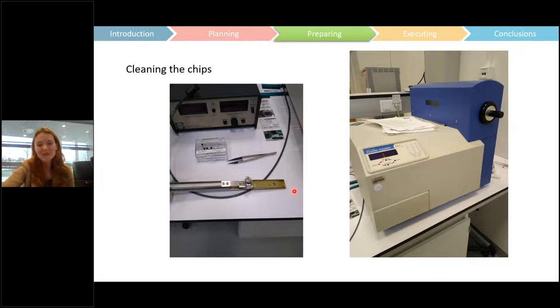If you can find somewhere to make you something like this, I would really recommend it, because trying to slide them in on glass slides is not the easiest thing to do. As I said before, it's really important to make sure we never chip those silicon nitride windows when we're picking them up, because that is how you get the O-ring leaks most of the time. Those chips are sharp.